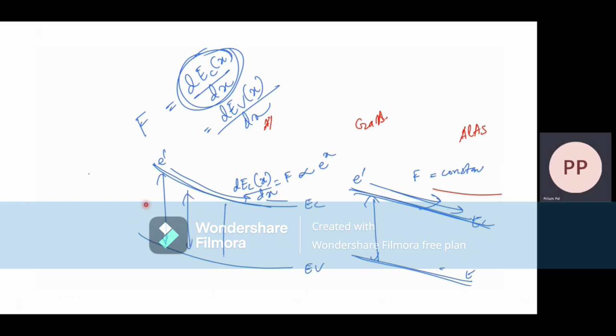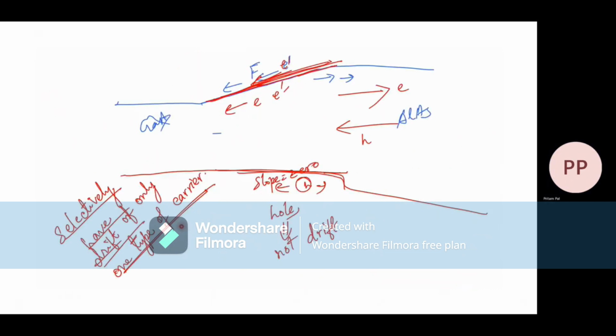And the way you practically grade this kind of thing is that you increase the aluminum composition. By the way, then it's not graded. This is not graded. This is only constant material, but with the heterojunction, you can actually grade it and make it even more. You have more flexibility for this case. Okay. What I mean by that is that when you are grading linearly, suppose you have something like, so this is aluminum arsenide, for example. Okay, this is gallium arsenide. This is aluminum arsenide. This part and this part we're forming the heterojunction.